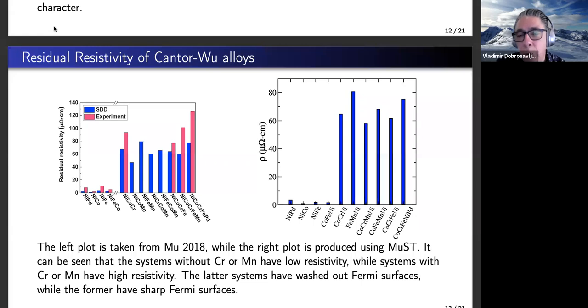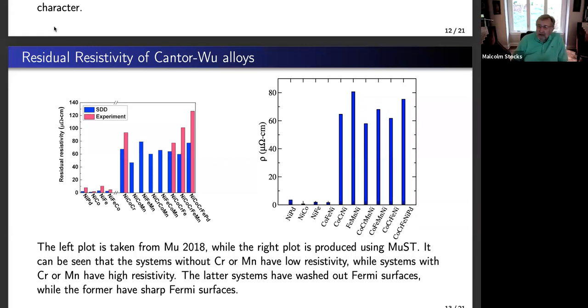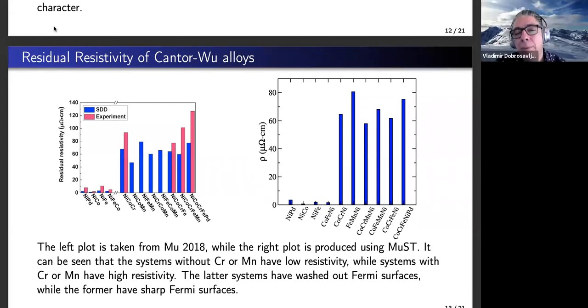That's basically what you do in the mean field theory for spin glass ordering. So more formally speaking, if you want to capture magnetic order within single site theories, you can do what they call EDMFT. In other words, the cavity can acquire a magnetic moment, but in random systems the internal field from a cavity can also be randomly distributed, and that can be done self-consistently, like Malcolm is describing, capturing this within a single site type of theory.